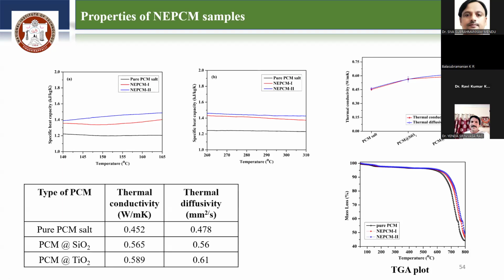centigrade. So, based on this TGA result, the onset degradation temperature of pure NEPCM1 and NEPCM2 samples, we can say around 590 or 600 for NEPCM1, and somewhere here around 610 or 11, okay, for NEPCM2 samples.